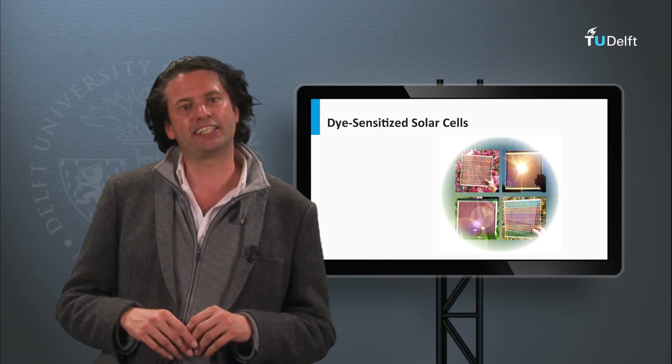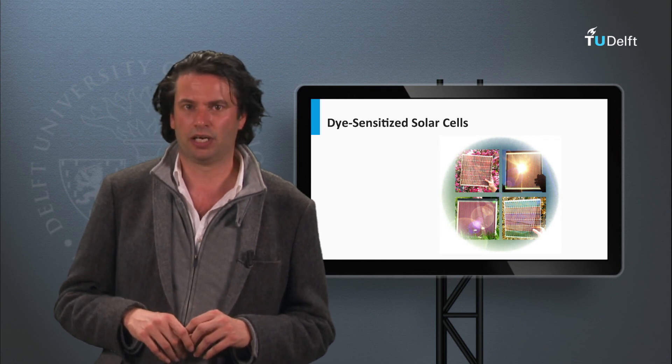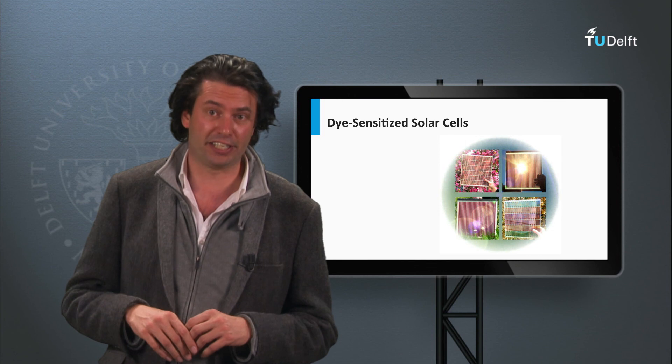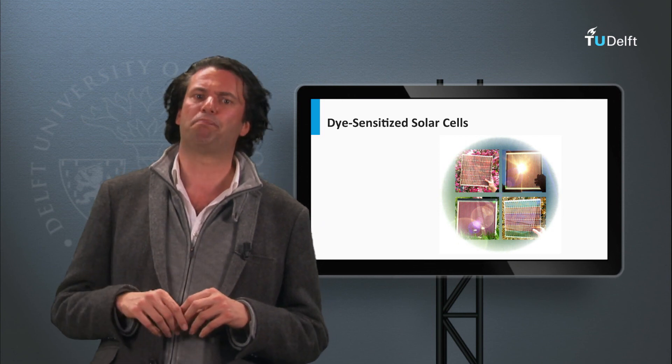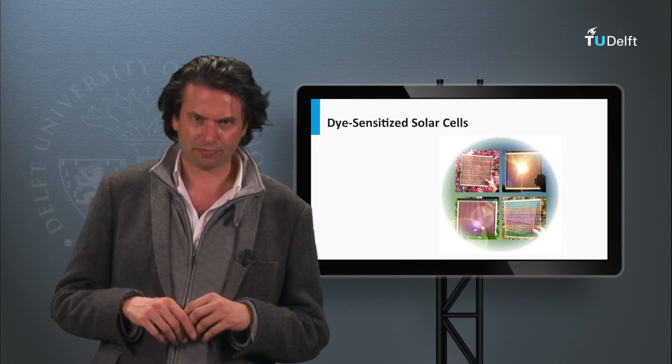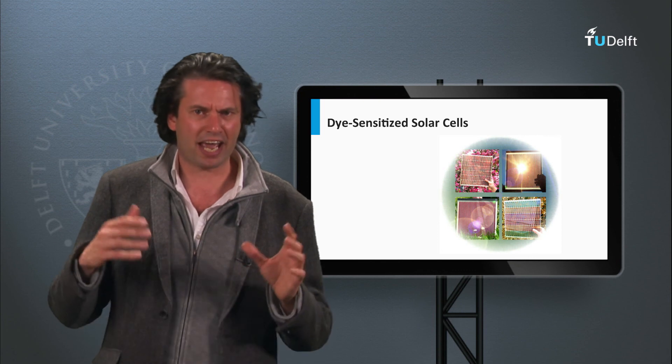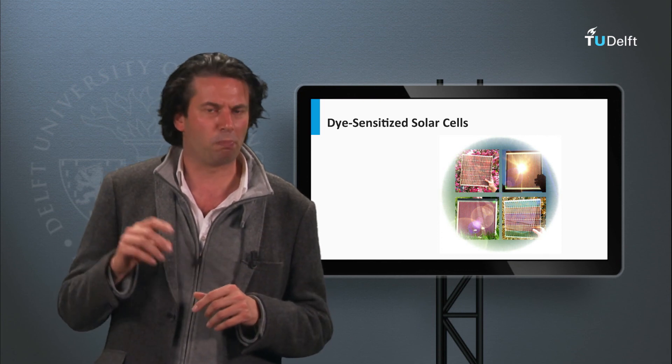A disadvantage is the stability of the electrolyte under various weather conditions. At lower temperature the electrolyte can freeze. This stops the power production and it might result in physical damage. Higher temperatures result in significant expansion of the electrolyte, which makes encapsulation of modules more complicated.